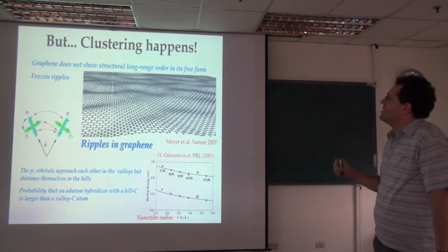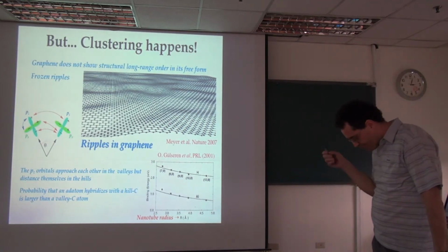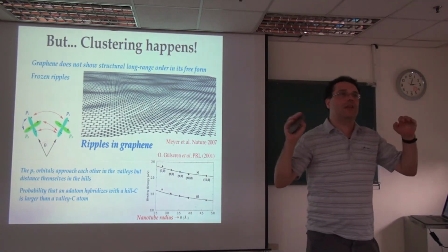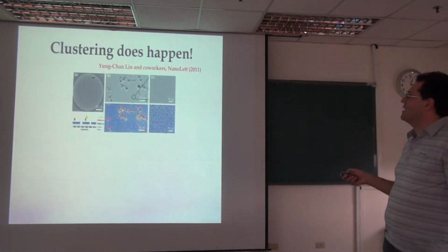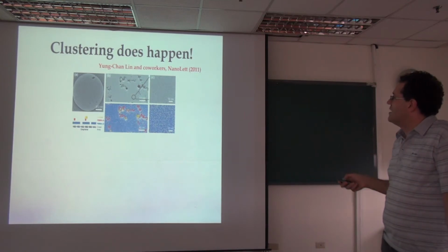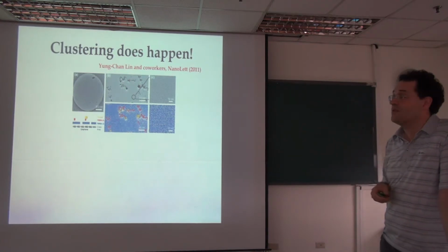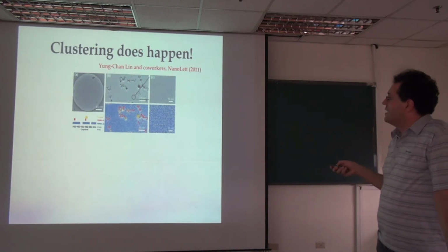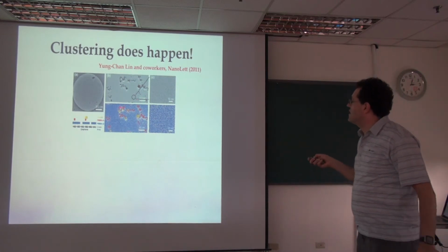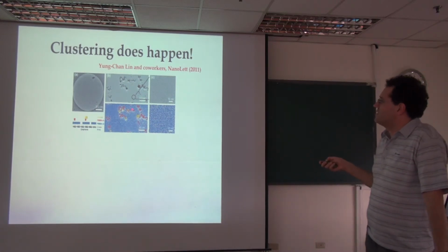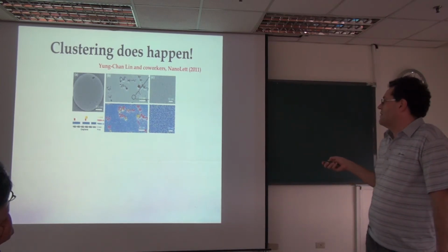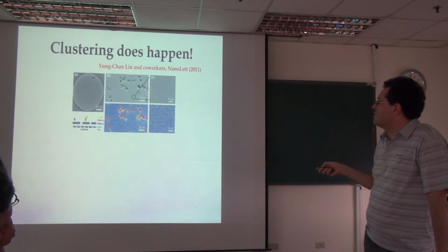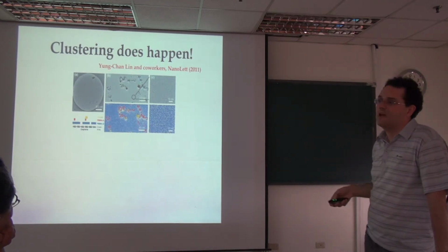So when you deposit atoms on the graphene sheet, they are going to cluster, and that must be important. And actually, my colleague Paul Chu in NTHU has beautiful pictures, not of hydrogen, but of copper, which appears in a certain process used to manufacture graphene these days, and this copper actually clusters and can form clusters of sizes up to 15 nanometers, which are quite big.